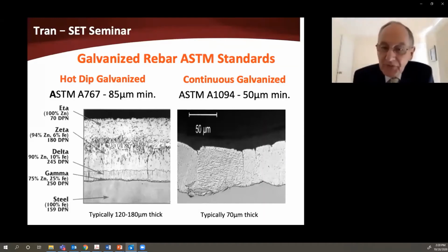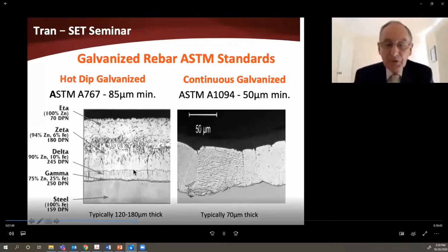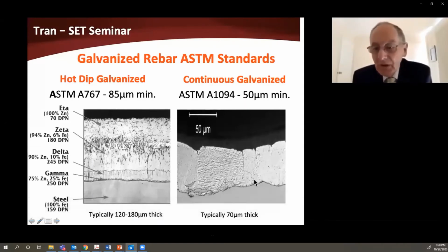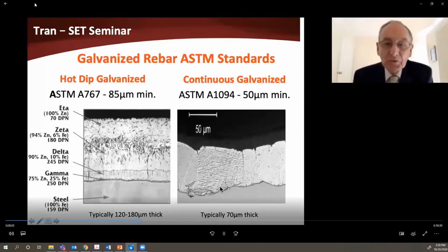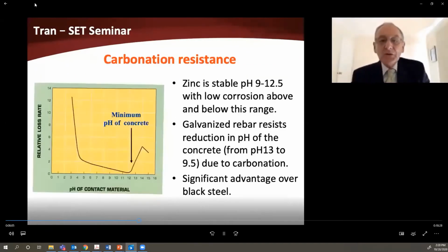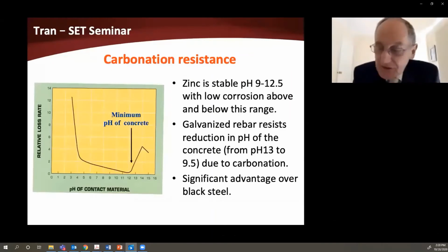molten zinc bath and the small alloy additions that are made to the bath of aluminium, these layers that form in the longer period of time for batch galvanizing don't form with continuous galvanizing. So essentially, it's a pure zinc coating on the outside, and that allows it to be quite formable. Now, let's talk a little bit about what happens with zinc in concrete now.